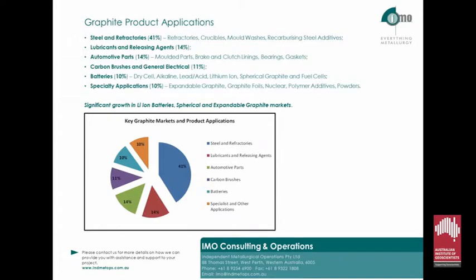Whilst talking to different companies will result in different answers on graphite product demand, IMO was engaged by Triton to conduct a marketing study and determine product testing requirements for graphite products. This resulted in the primary demand being for steel and refractories. Feedback we received from attendees at the most recent London Graphite Conference is that graphite use in the recarburizing market is essentially non-existent due to the price of high-grade graphite being overpriced compared to other suitable available carbon products. Most of the current excitement we see in the graphite market is confined to the expected increases in graphite consumption in lithium-ion batteries, spherical and expandable graphite.